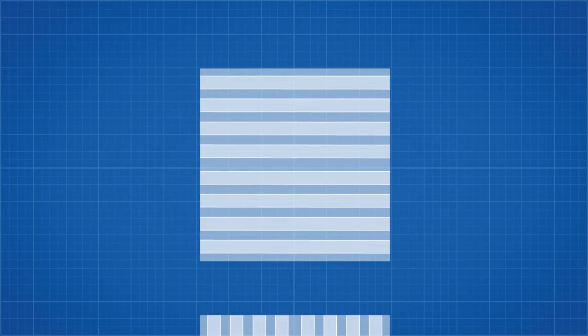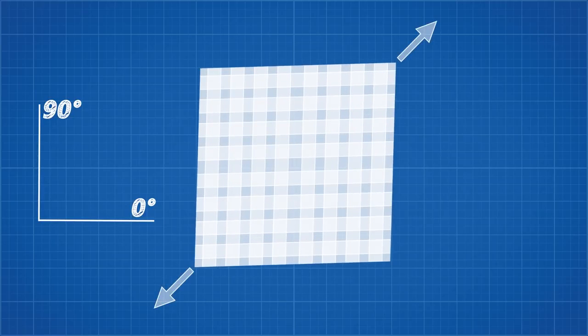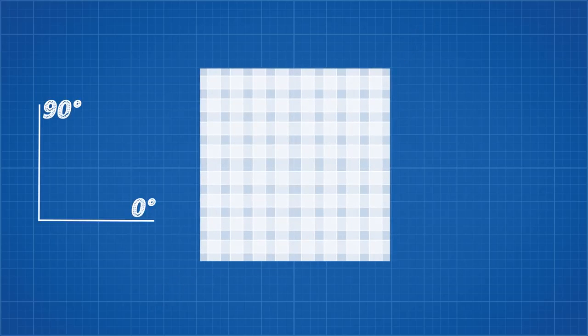To combat this, engineers will layer the fibres on top of each other. Here we have a 0-degree layer on top of a 90-degree layer, so the material properties are the same in those directions. But now the 45-degree direction is weaker. We can keep adding more layers until we have similar stiffness in all directions, but eventually the thickness of the material will become too great. We reach another problem when we remember there is nothing but the resin matrix holding these layers together, and sometimes that fails and we get delamination of the layers.